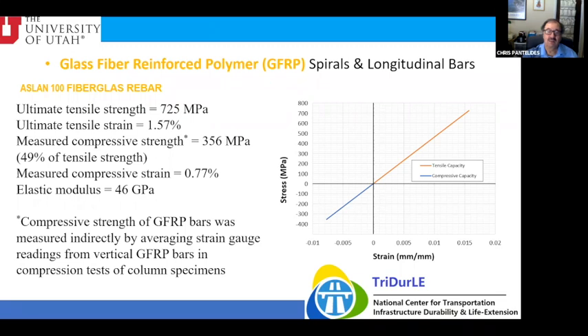The way we did that is we measured it by averaging the strain gauge readings from the vertical bars in the compression test of our column specimens. Measured compressive strain is about 0.8%, and the elastic modulus is 46 gigapascal.